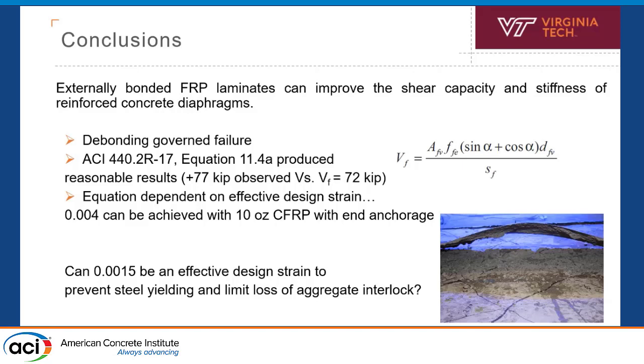Again, this equation's dependent on what strain you choose. So we chose 0.004 just to get, you know, where's it going to break at, and that was accurate for a 10-ounce fabric that's anchored on the ends. That may not be true for denser fabrics or different anchor configurations. And again, I want to hammer this home. I think 0.0015 is a better strain to be using for design.